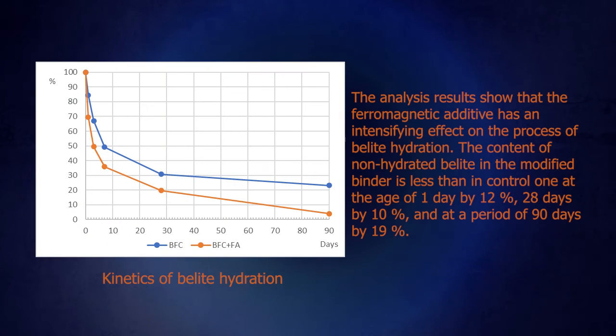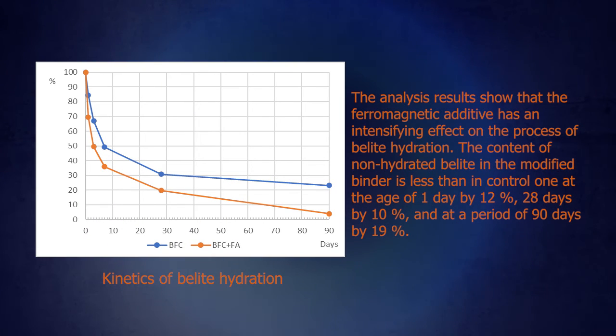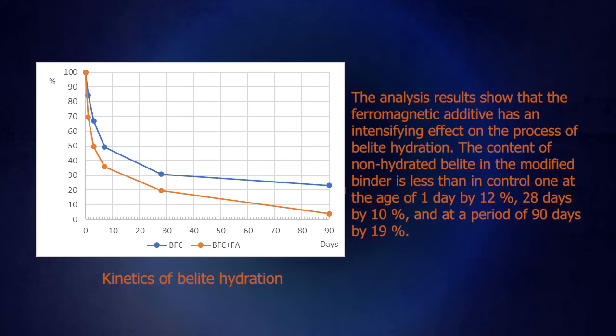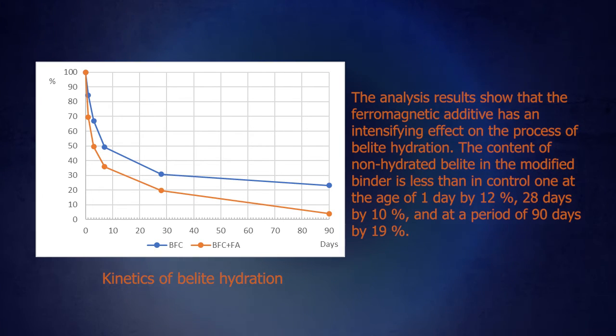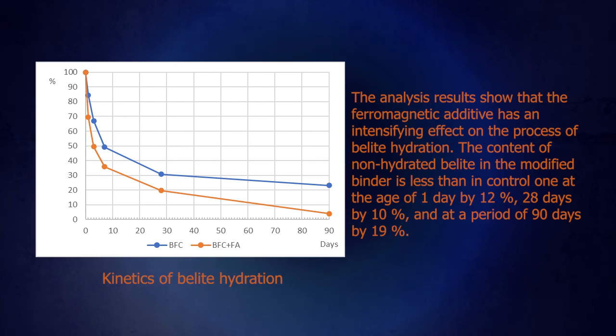The analysis results show that the ferromagnetic additive has an intensifying effect on the process of belite hydration. The content of non-hydrated belite in the modified binder is less than in control at the age of 1 day by 12%, at 28 days by 10%, and at a period of 90 days by 19%.